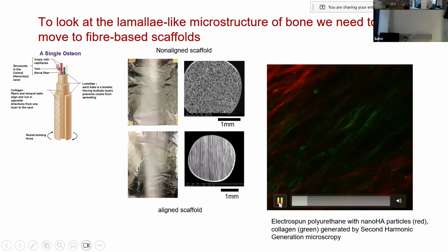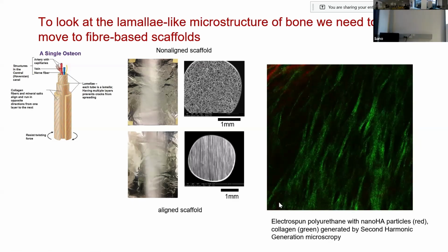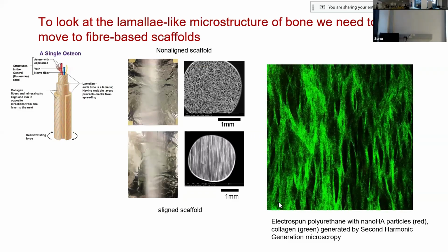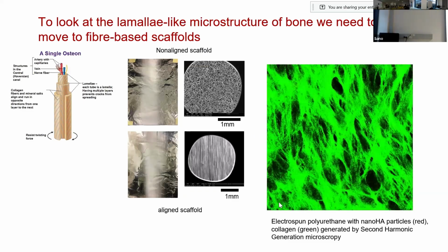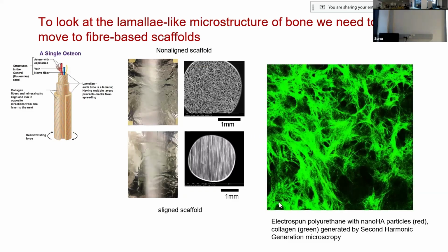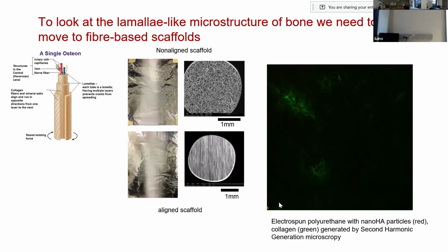The red fibers are the scaffold. The green fibers are the collagen, which aligns with the scaffold because it's being guided by these fibers here. But then as we grow and build collagen too far away from the scaffold, it stops aligning. It made more of a rounded honeycomb shape. So that guidance by those biomaterial fibers is helping the structure form more like a bone structure.